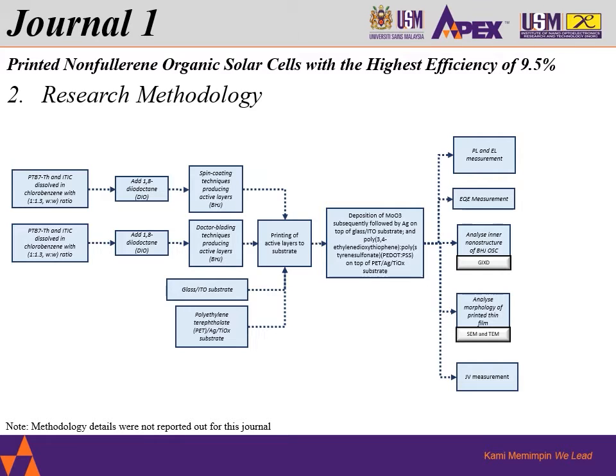Okay. So the active layers are already produced over here. And now we need a substrate. So over here, the glass or ITO substrate was selected. This is the first substrate. And then for another one, we would have the PET, silver, or Ag, and TiOx substrate. So these two substrates will go, and each of the active layers will be printed on top of each of the substrates. So you can imagine that there's like a 4 matrix over here. And then all of this will go into the deposition of the consequent layers, which is the deposition of MoO3, followed by silver on top of the substrate, respectively.